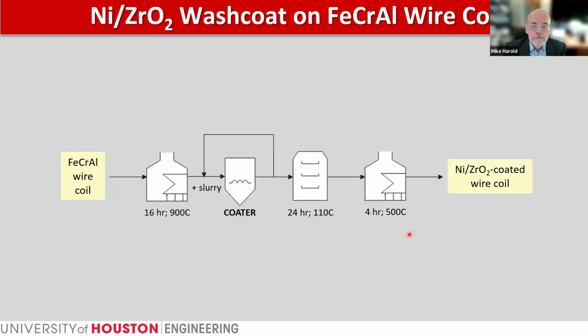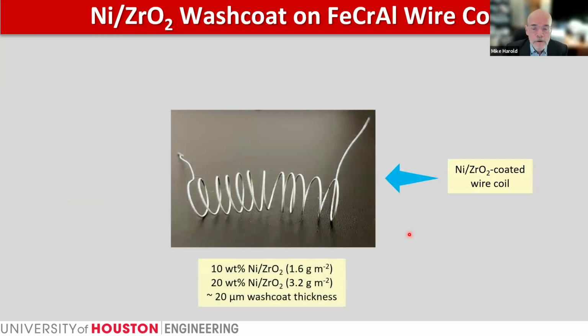Now, the experimental setup is straightforward. First, we make the catalyst. The catalyst will be nickel-based on either zirconia support or alumina. The choice of the support, as I'll show today, is critical. Now, we do this coating in Professor Praveen Bollini's lab with his student Meghana, producing a coated FeCrAl wire with a very thin layer of nickel zirconia. Now, the wash coat thickness, depending upon the gravimetric loading, the mass per area, is nominally 10 to 20 microns thick, not unlike the wash coat that we would see in a catalytic converter in our car.